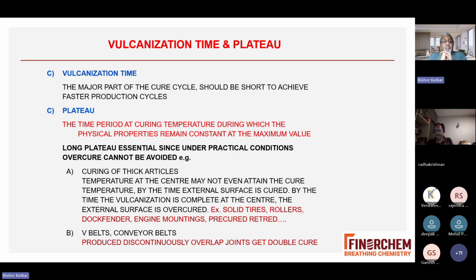Curing of thick articles. The temperature at the center may not even be attained. When you have thick articles like dock fenders, solid tires, rollers, engine mountings, pre-cured treads, what will you observe when curing these? When curing a thick article, the temperature at the center may not attain the cure temperature by the time the external surface is cured. And by the time vulcanization is complete at the center, the external surface is overcured. So this is a very practical problem.